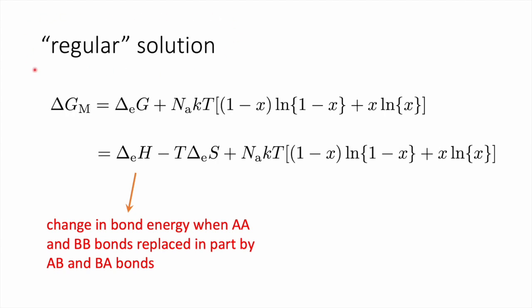Now, a regular solution is a solution in which there is, in fact, a finite enthalpy of mixing. So when you break AA bonds and BB bonds and form AB bonds, there is actually a change in energy associated with that. So, in addition to the ideal solution free energy of mixing term, we have a second term here, which is the excess free energy of mixing that consists of two terms here. The enthalpy change when we form new bonds, and contributions from entropy, because thermal vibrations, etc., may make contributions to entropy other than just configurational entropy. So if you focus on this, this represents the change in bond energy when an AA and a BB bond is replaced in part by AB and BA bonds.